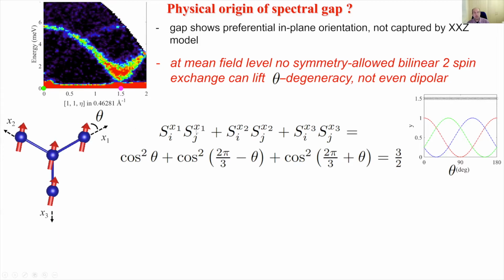So that's an S_X1, S_X1 interaction. Now, by symmetry, there must be an interaction for this bond, that's S_X2, S_X2, and similar for the third bond. So if this is added up, it comes out to adding 3 cosines with a 2 pi by 3 offset. And even though it's cosine squared, and even though each one depends on theta, the sum of them is constant. And one can show more generally that for any type of bilinear couplings, there's no mechanism at the mean field level to have the energy depend on theta.